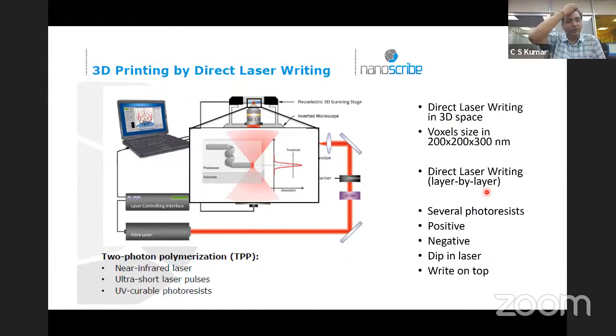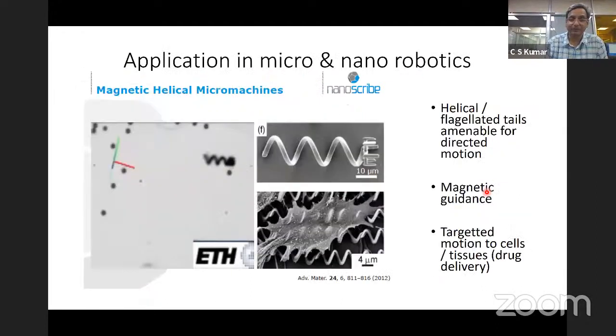So it uses a technology called direct laser writing, wherein you focus a small beam of light and you modulate its intensity and amplitude by a process called 2-photon polymerization. It's a near infrared laser having a wavelength of about 760 nanometer, 780 nanometer, which at half its length you can get its resolution. You can work with photoresists like positive, negative, and you can write on top or use a dip-in laser process. The voxel size is 200 by 200, 300 nanometer, and you can directly build parts in 3D.